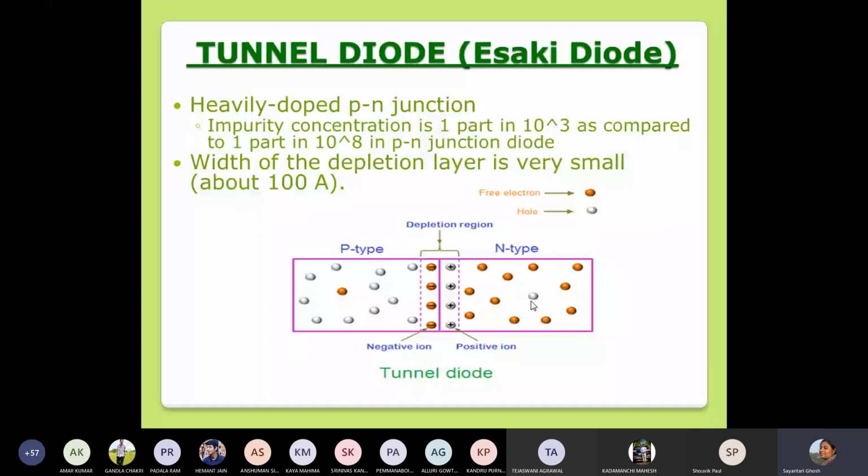So what could be the effect of this doping that comes into our mind is obviously the depletion region. By now we have discussed depletion region formation and doping levels so many times while discussing FET. I guess the first thing that you understand is that the depletion layer that we have here is going to be very, very thin, right? As soon as you have a PN junction where the concentration of impurity is very high, then very soon the barrier potential will be high enough so that no current can further flow, and the depletion region will be quite thin.